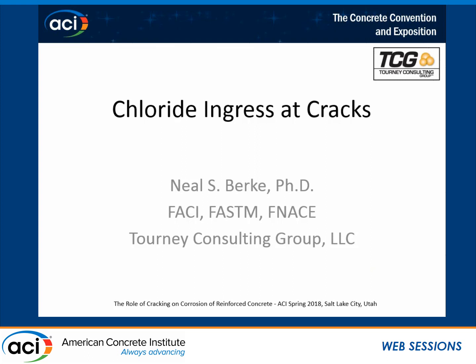So I'm going to talk about not corrosion per se today, even though the samples I'm looking at all had corrosion work done on them. And I will say that they all went into corrosion much quicker than they would have if there had been no crack. So the crack definitely caused corrosion to initiate early. But I'm going to talk more about how the type of bars and the type of cementitious material you use might affect how fast that chloride gets through your crack.